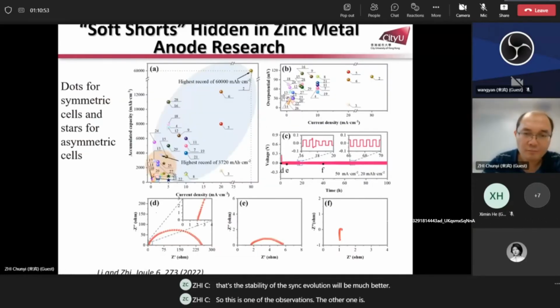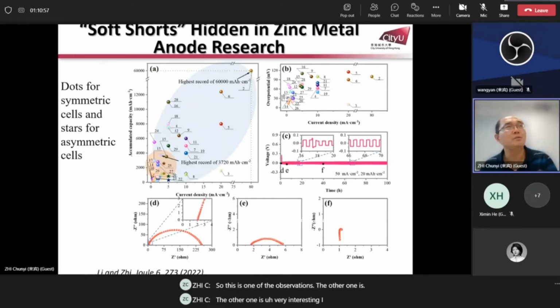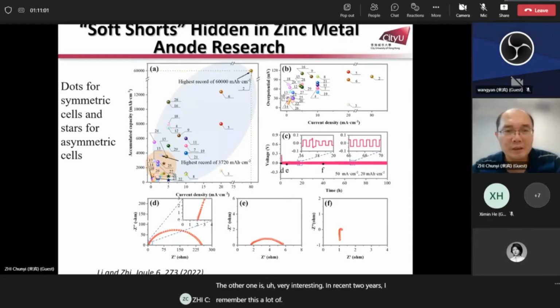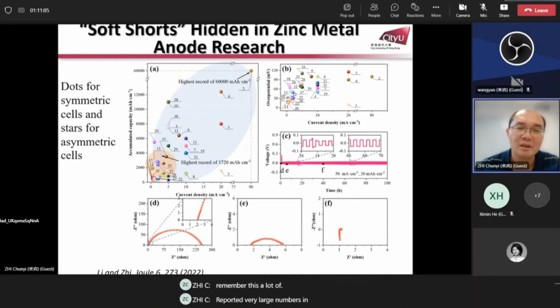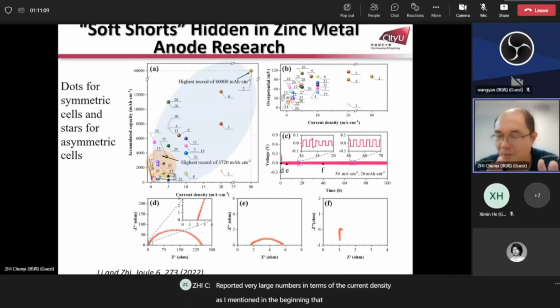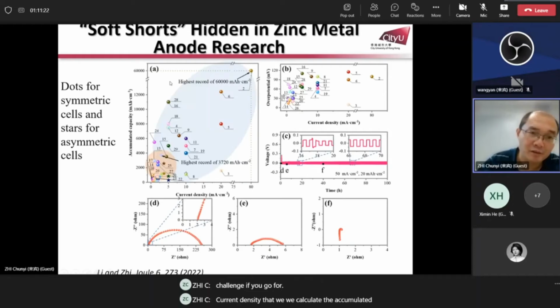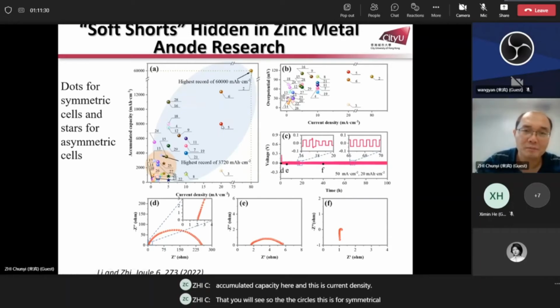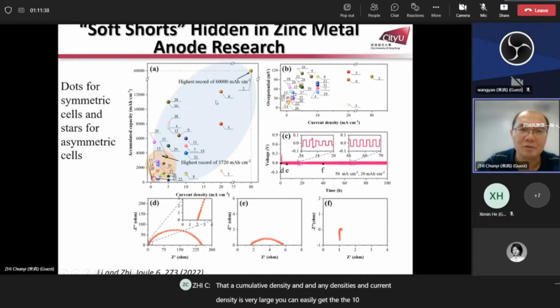The other one is very interesting. In recent 2 years, I remember there are a lot of reported very large numbers in terms of current density. As I mentioned in the beginning, current density is a challenge, and areal loading mass is another challenge. If you go for current density, we calculate the accumulated capacity here, and this is current density. You will see for the circles, this is for symmetrical batteries, the accumulated capacity and current density are very large. You can easily get 10,000 times of accumulated capacity, and the current density from 10 to even 80. That's insane. And for some stars, this is for non-symmetric batteries. Well, the contrast is very large.